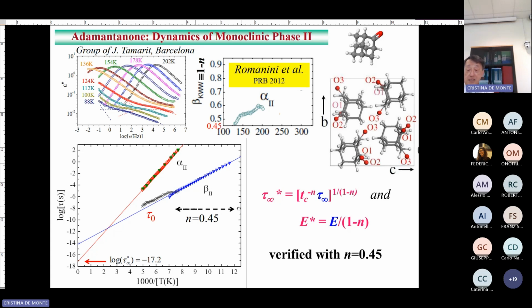And when you look at this equation, you can calculate with a known exponent here, because it's known. You can see that 1 minus n is plotted as a function of temperature. And then you know the alpha relaxation time, which is now given here in the relaxation map, together with the beta relaxation further down at lower temperature. They found this Arrhenius one.